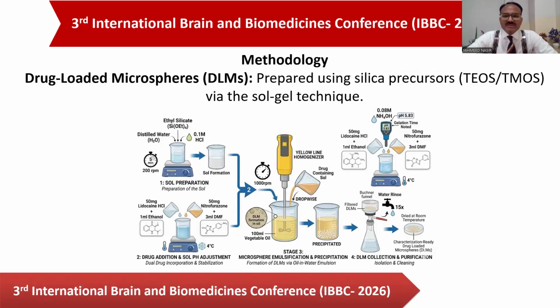The methodology I adopted for the sol gel technique, as I discussed earlier: the sol is first prepared and then it is converted into gel and microspheres are prepared. Now, if I discuss briefly, then sol preparation contains distilled water, ethyl silicate, or tetraethyl orthosilicate, which contains the silica, and 0.1M HCl. In the second step, the drug solutions were prepared, and I incorporated them into the sol. And the prepared sol was added drop wise into the vegetable oil. And then a homogenizer was used at the speed of 1000 rpm to obtain the microspheres.